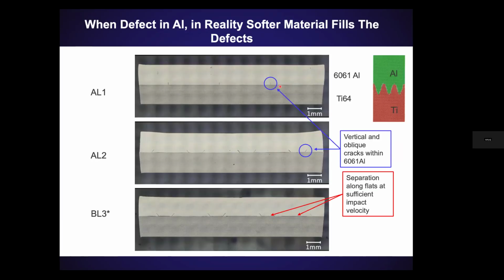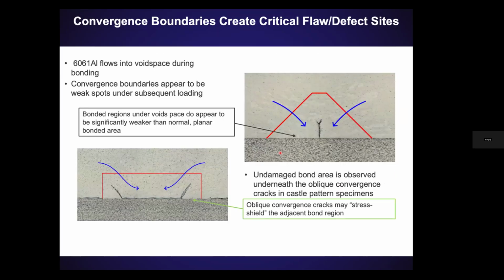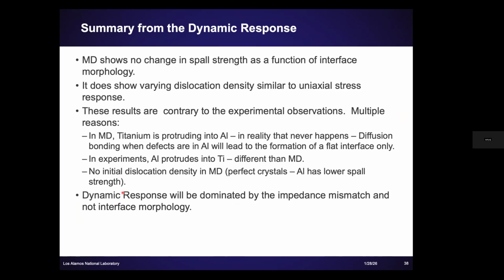Another interesting thing was that how you made the interface really mattered too. In cases where we put the defects in aluminum, which would be right here, and then bonded them to try to create a rough interface, the aluminum just filled those defects, and those interfaces essentially just acted like a flat interface. So we could switch on and off the dynamic response of these interfaces by having a flat interface versus rough perturbations at the interface. This is a zoomed-in image highlighting that we had a defect in aluminum. When we diffusion bonded them, the defect heals, and everything essentially looks like normally bonded material.